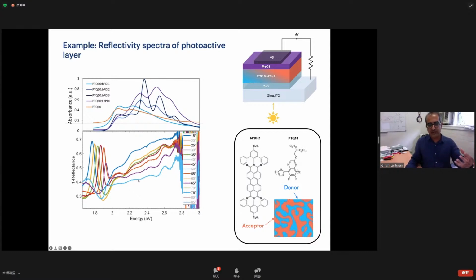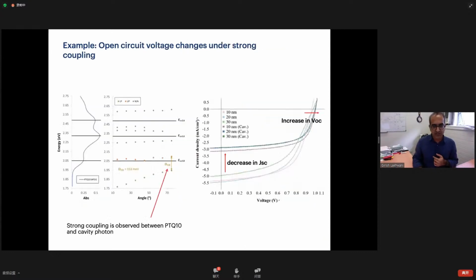Here they're shown, where you can see these photonic fringes. You're seeing patterns that come from the photonic cavity. And what you're doing is not only enhancing the absorption, but also changing the potential energy surface, which is shown over here. What we see effectively is that we can split the energy states just by putting these molecules in a cavity.